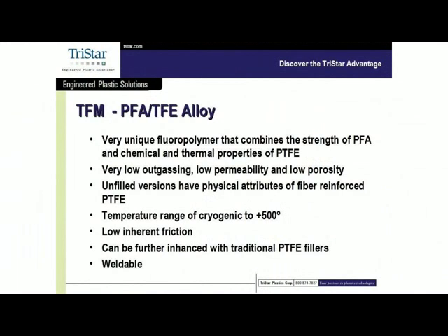Next one is TFM. TFM is another fairly unique polymer. It's actually an alloy between a PFA-like material and PTFE. So what makes that unique is that you get almost all of the properties of PTFE, but in the form of a melt-processable material. This is a material that we can actually spin weld. For instance, you can spin weld a PFA fitting into a TFM housing, and just the heat from that spinning process will weld the fitting to the body, and so you have a seamless joint. Very unique property of TFM.